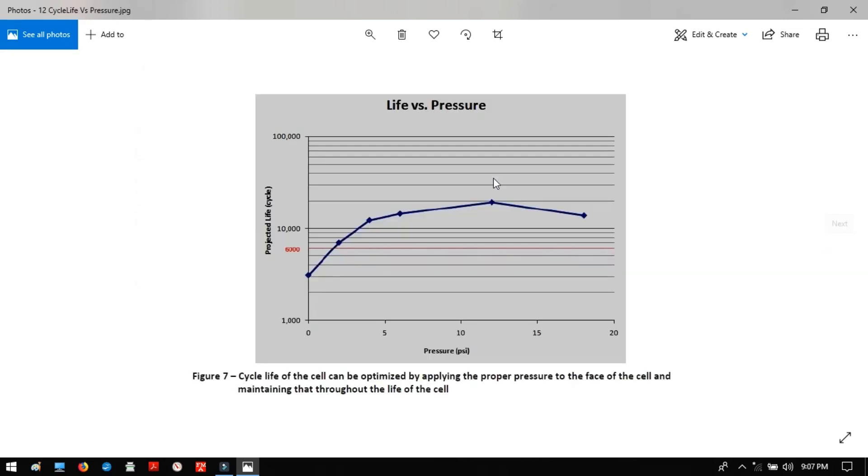And that's an example there of that. In this example, we're seeing where they held the temperature the same and the window, the state of depth of discharge and so forth is the same. And there are two cells that were tested and they were all discharged the same, 1C, but they were charged at different rates. So two were charged at 1C and we see that they pretty much lined up and did pretty much the same. Two at 3C and two at 4C did very similar here. And then two at 5C also did similar. We're not trying to do the specific numbers. Don't get hung up on that. You want to see the overall trend here where the same cell and the same temperature and the same window and otherwise same conditions just by charging it faster, just doing 5C instead of 1C, this is the total throughput.